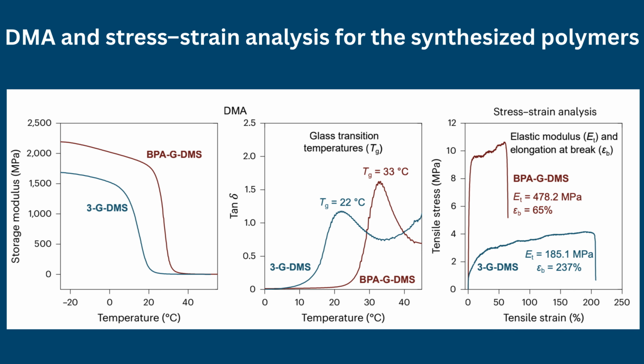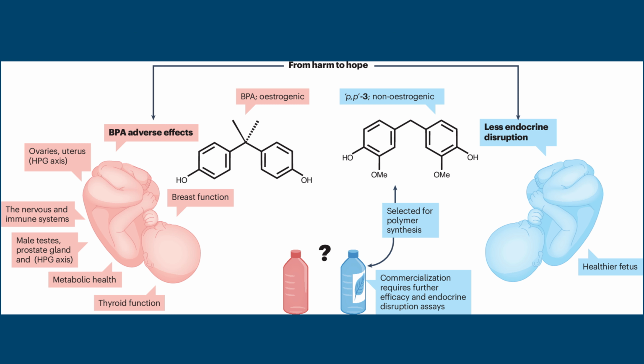Mechanical performance. Mechanical testing demonstrated that the BGF-derived polyester exhibits lower stiffness, but significantly higher elongation at break, indicating enhanced flexibility and ductility. These properties make it particularly suitable for applications requiring soft, deformable materials, such as flexible electronics, robotics, and biomedical devices. This study highlights several critical insights.